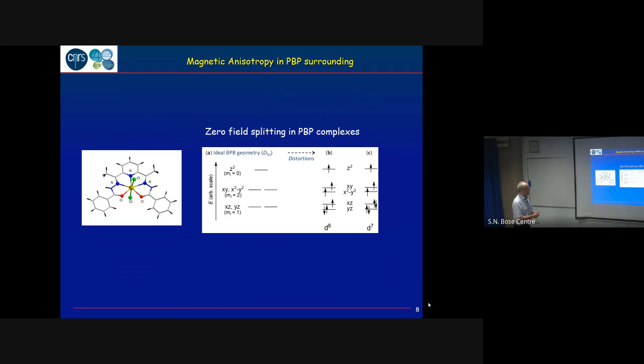In such a geometry, what I show here is the energy diagram of the d orbitals in the ideal D5h geometry. Of course, in real systems, you are not exactly in the perfect geometry. So the reality is that you lift the degeneracy of these levels, and the real picture looks like this one. If now you have a given electronic configuration for your metal ion, so you put the electrons, and if you are in the right situation, you can expect some anisotropy that is simply coming from the zero field splitting.